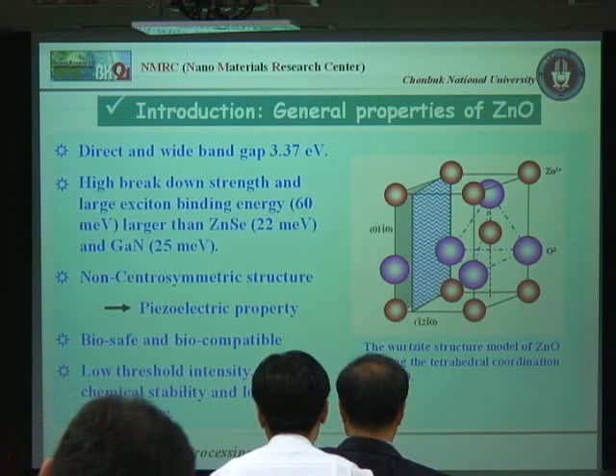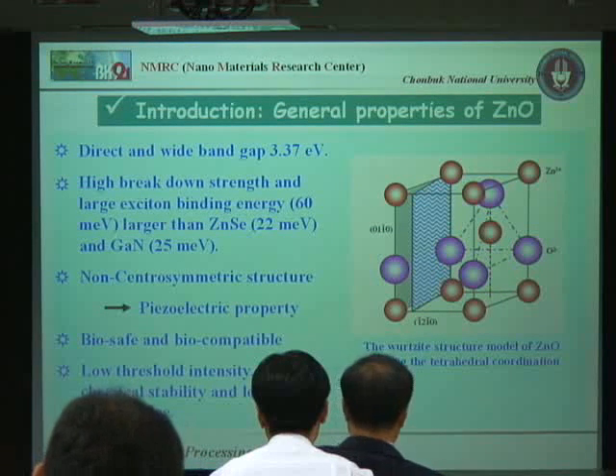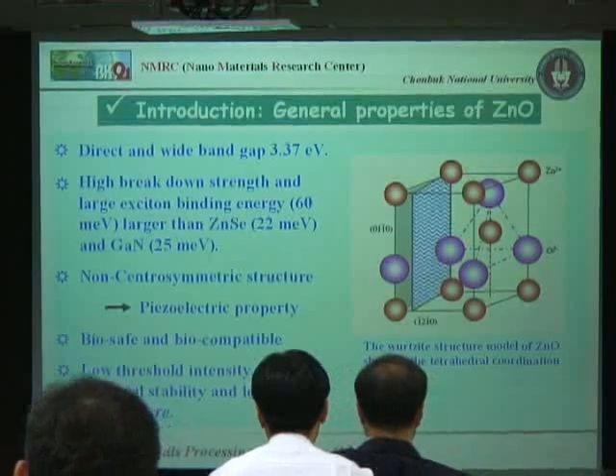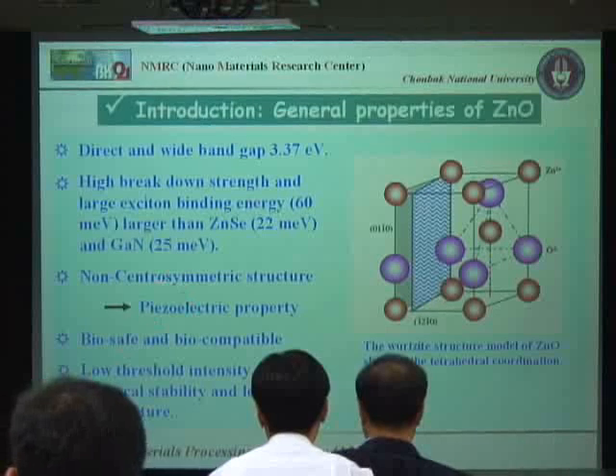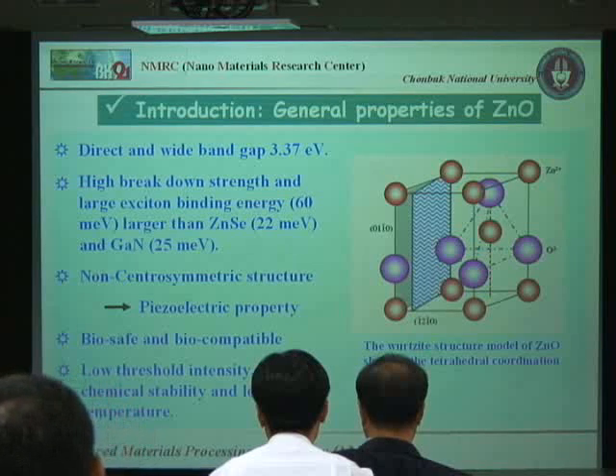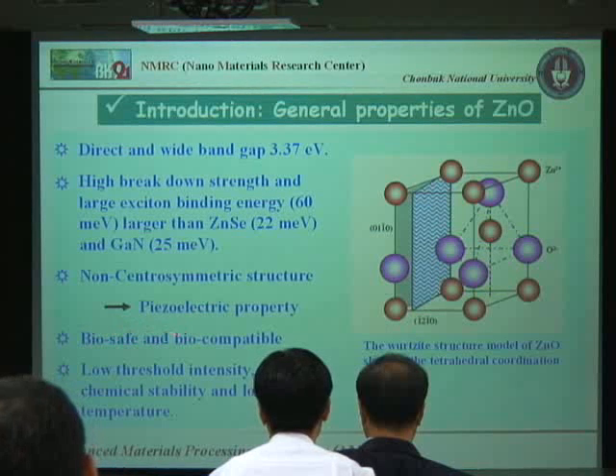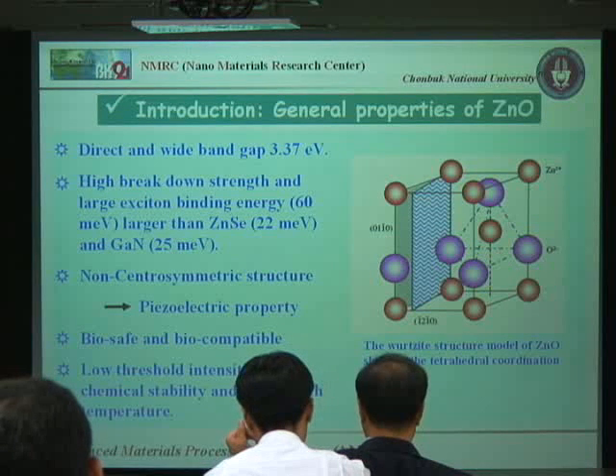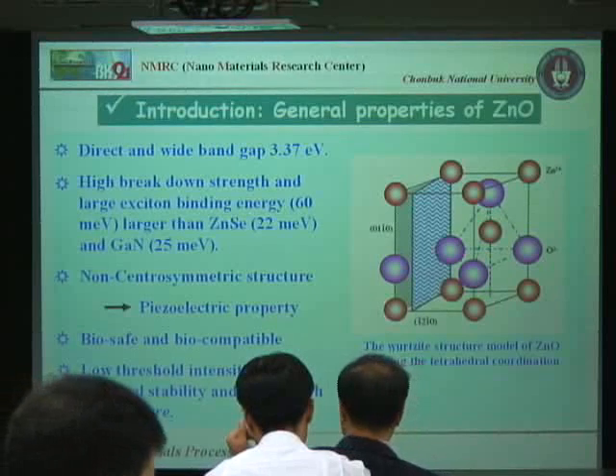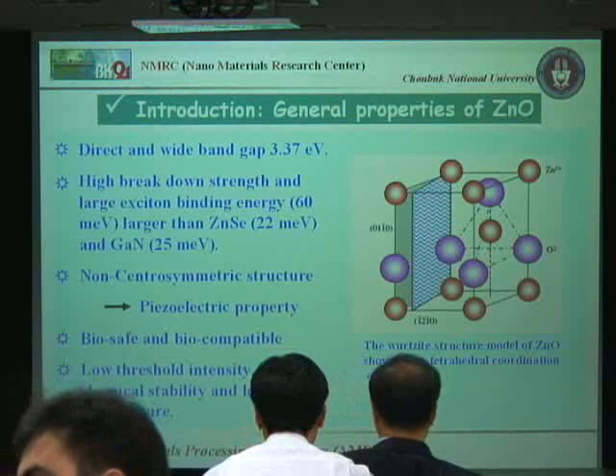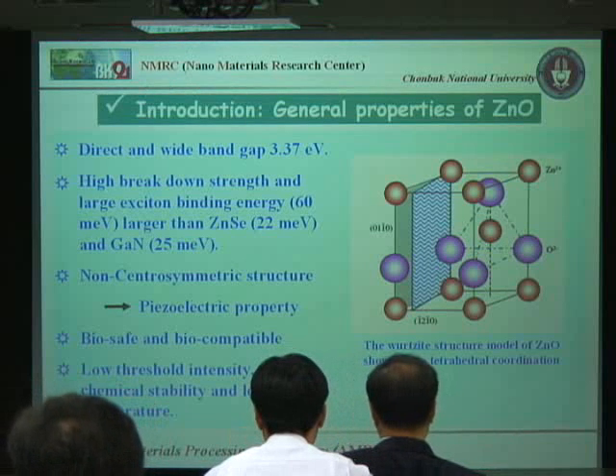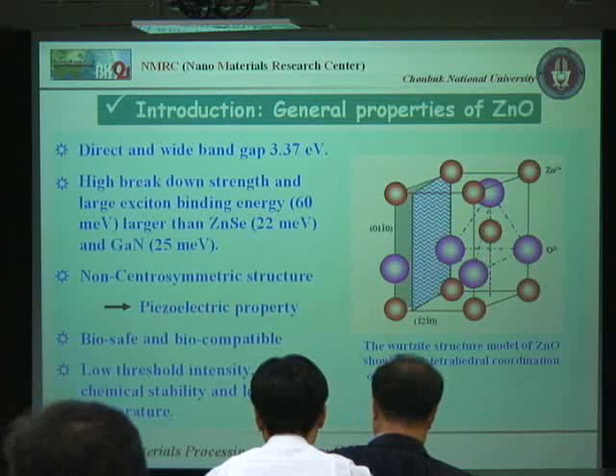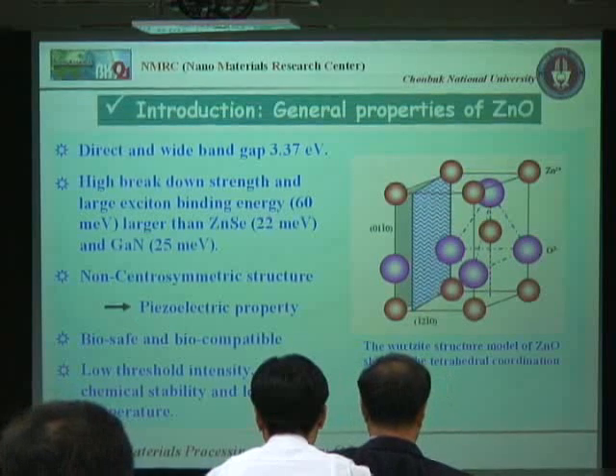In terms of its structural characteristic, it has a non-centrosymmetric structure, which is very important for the piezoelectric property. Because of this, it is applicable to fabricate some piezoelectric devices and actuators. Furthermore, it is also biosafe and biocompatible, and it can be used without coating for further biochemical applications. The low threshold intensity, high chemical stability, and low growth temperature of zinc oxide make it an important material for future research and application.